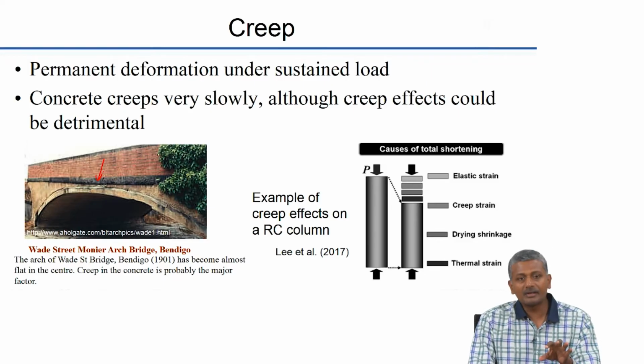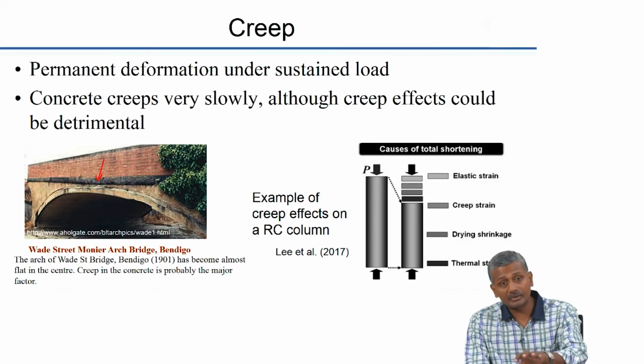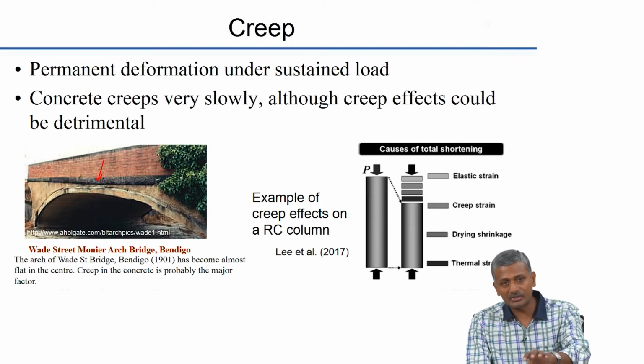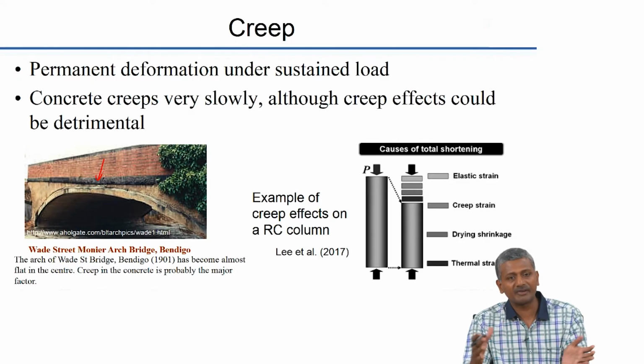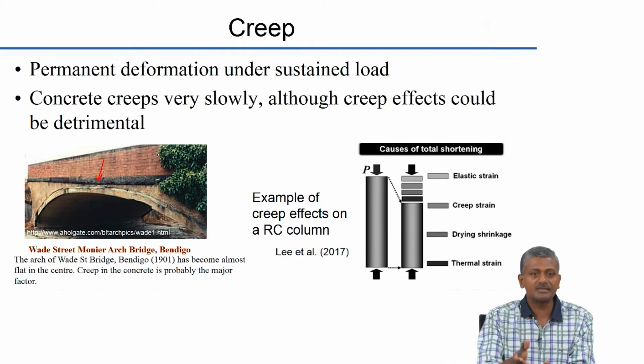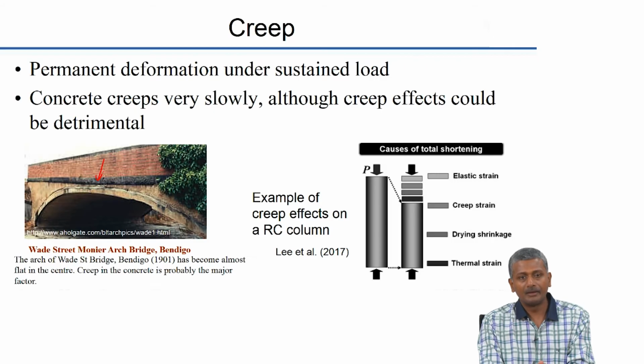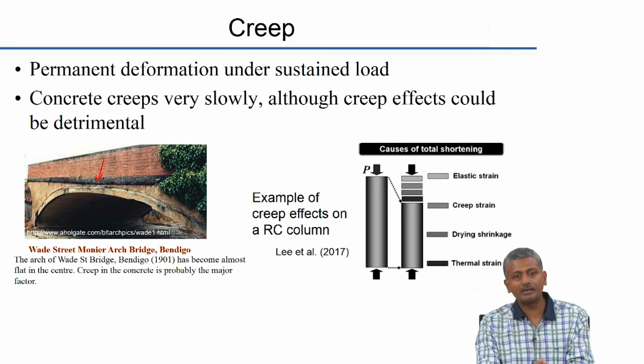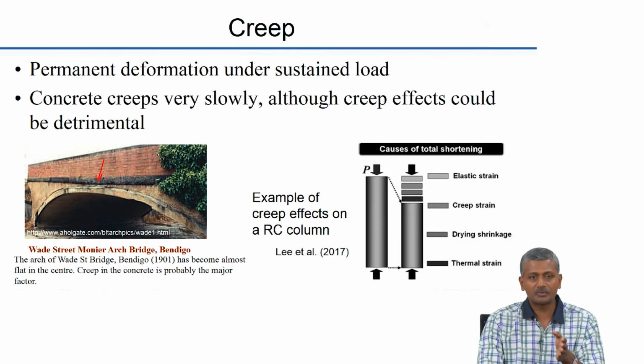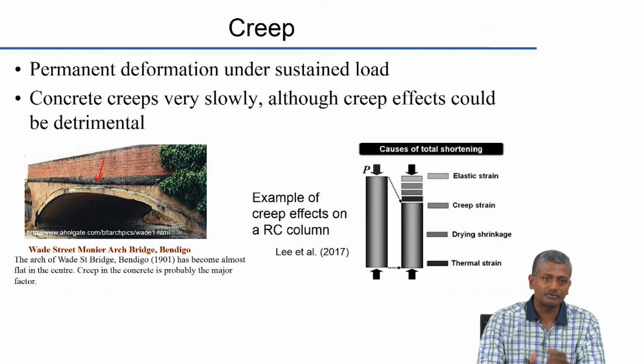The strength may not increase because of that. In the case of CSH, yes, when you are talking about CSH, the strength will increase because of consolidation, but the overall deflections are so high that your failure strains are going to get reached much easier than without any creep. In the case of metals, the internal rearrangement can lead to a reduction of stress concentrations, which may actually lead to an improved performance in certain instances, but that depends on the type of loading, on the type of stress that is actually existing in the material and so on.